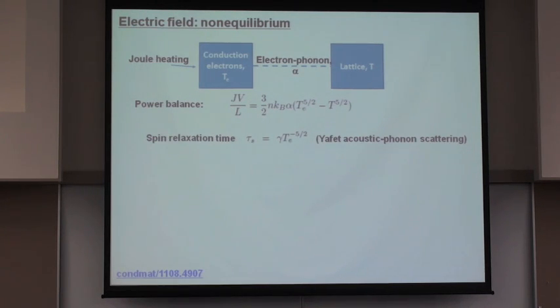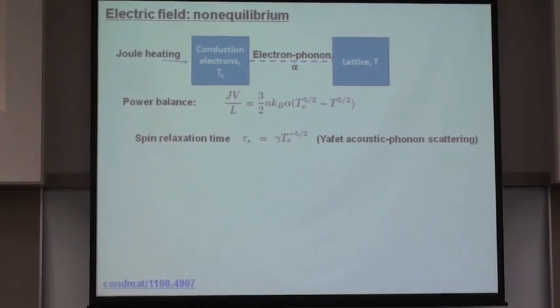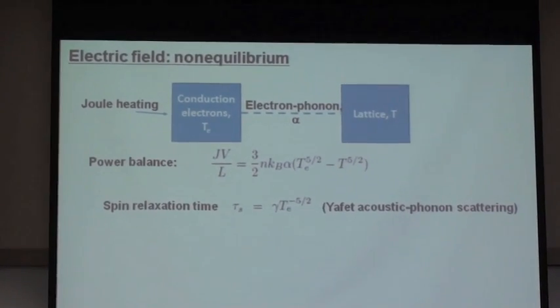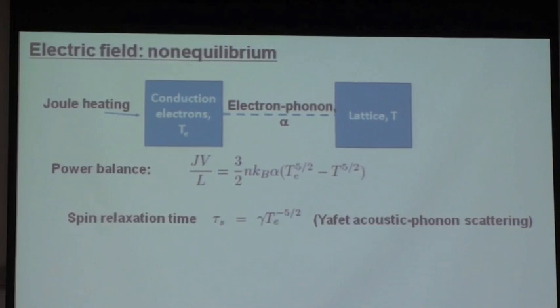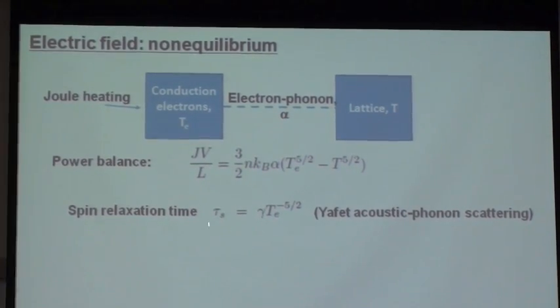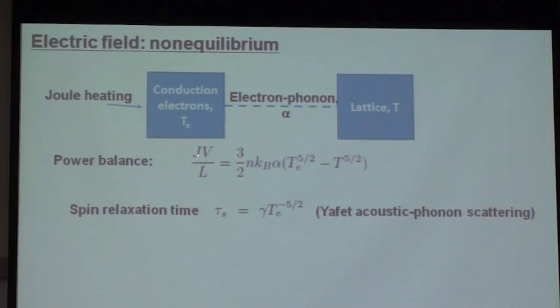Previously, as I said, we were using very low electric fields in which the electron ensemble was in equilibrium with the lattice. Now, what happens if I try to drive these electrons very, very strongly with strong electric fields? Well, if we look at this power balance equation, we see that as we drive large currents at large voltages, what we're doing here is we're dumping energy into the electron ensemble, and depending on its coupling with the lattice, we can actually drive an asymmetry such that the electron temperature rises with respect to the lattice bath that's held fixed.